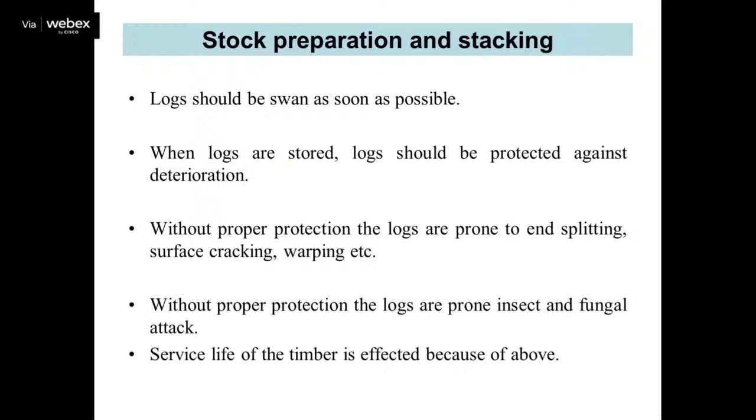If we allow the logs to remain in the open for a long period of time, exposed to the temperature, it is possible that the moisture will come out from the end. This abrupt escape of moisture from the end may cause end splitting, causing damage and loss of the timber. Therefore, for proper protection, these logs should be end protected.